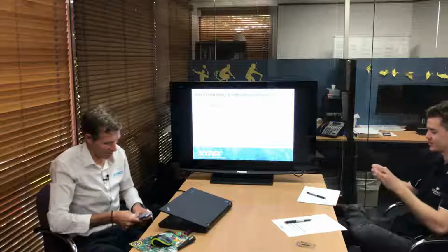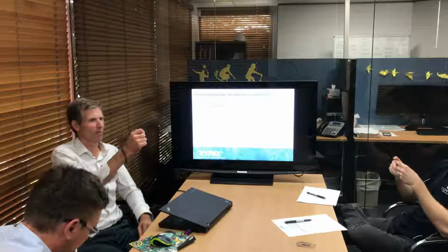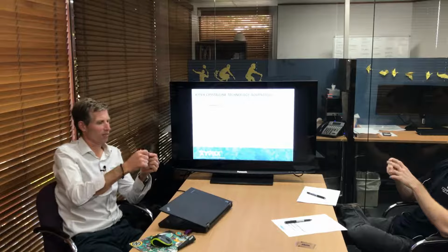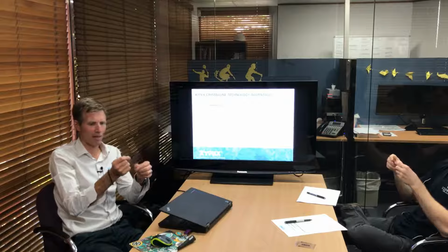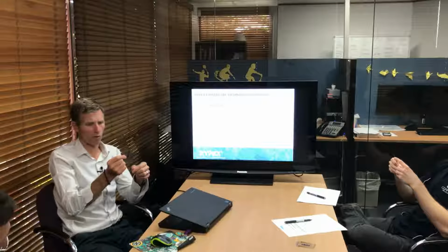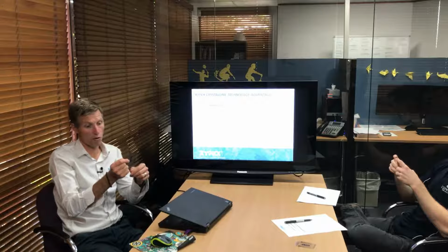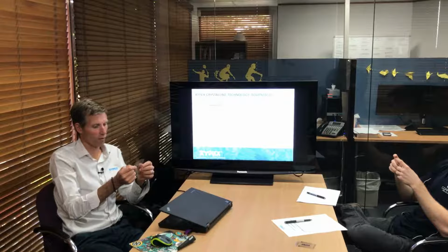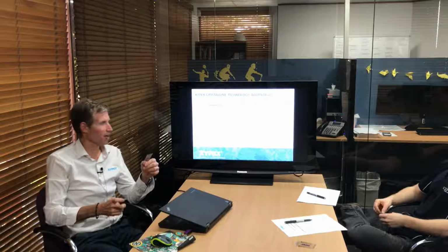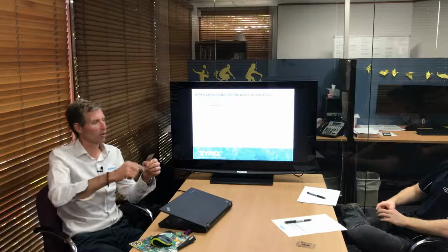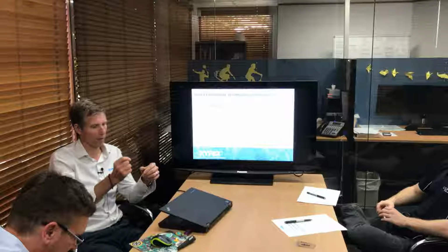Essentially, Xypex will self-heal static cracks up to 0.4 mm. If you hold that up, you say, oh, 0.4 mm. But 0.4 mm is actually a relatively big crack when you see it on a slab, especially a new concrete slab. And it is certainly outside the tolerance of, say, a typical main roads project, who get concerned about anything above 0.2 mm. So we cover more than that.